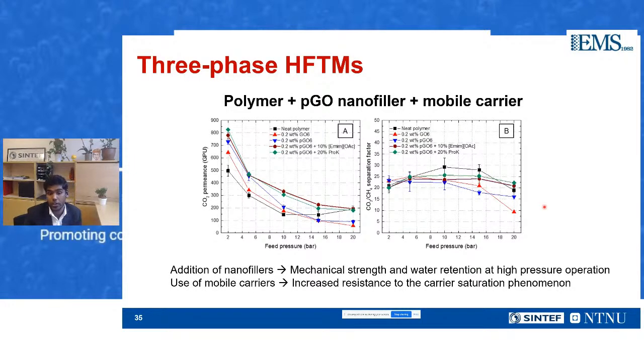bar of upstream pressure. And the water retention on this high pressure was also relatively good thanks to the hydrophilic nature of graphene oxide. But what exactly helped, like for example, when we look at this figure, what is the actual role of mobile carriers here? The mobile carriers is basically used to increase the CO2 solubility in the matrix and also diffusivity because of the mobile nature. But in here, they also help with the phenomenon called carrier saturation resistance.